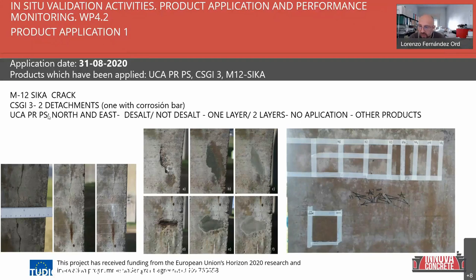didn't hit the sample. Also, we desalted some of the areas in order to apply the product, some desalted and some areas where we didn't desalt. Also, we did some samples of one and two layers, and we also applied other products in the market in order to compare their performance in relation to those products. Okay.